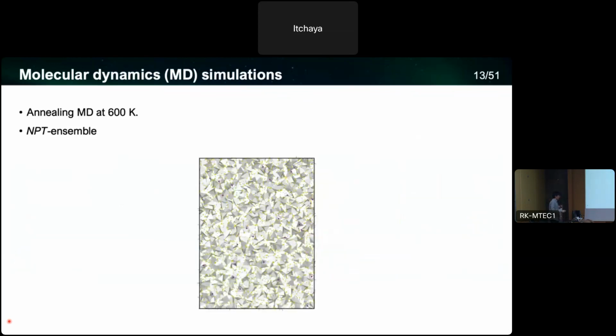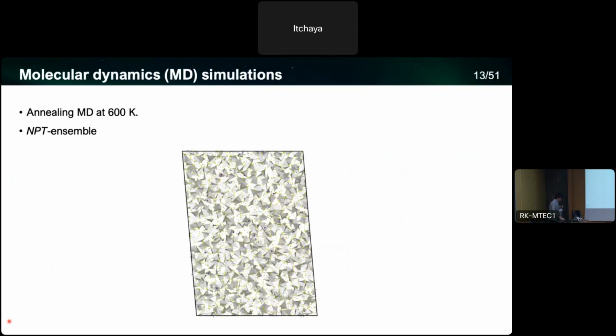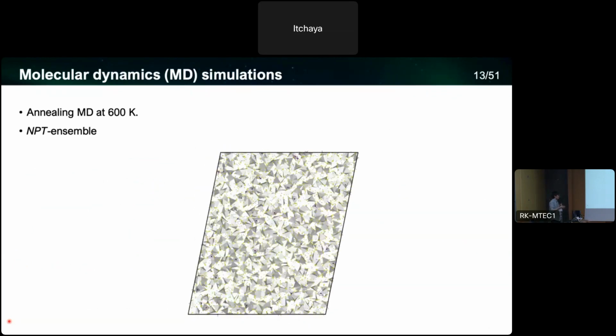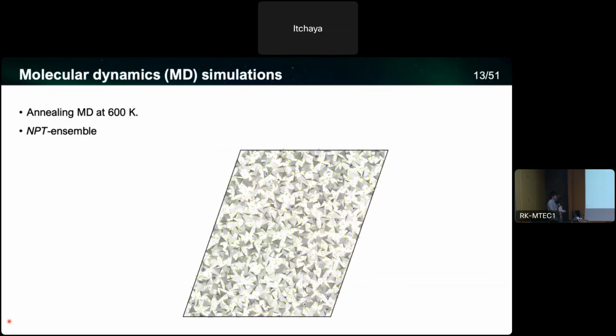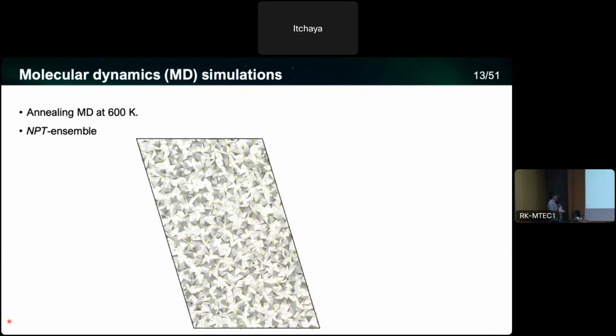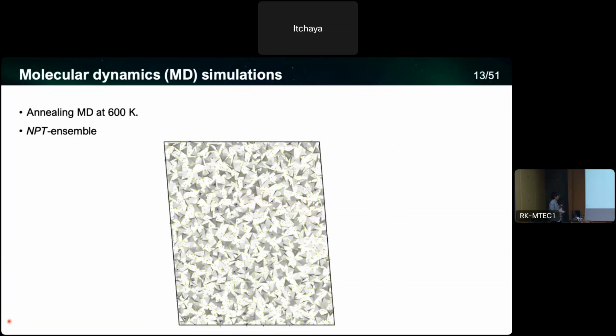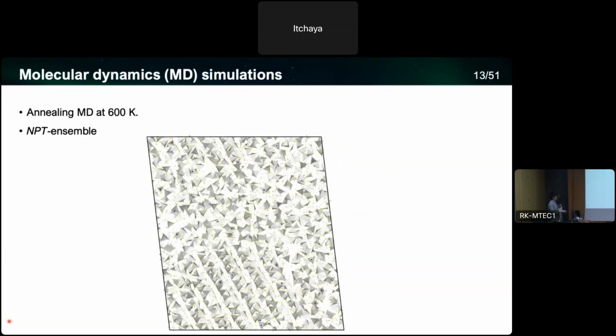Then from those glass structures, we need to do some heat treatment, again by molecular dynamics simulations. In this molecular dynamics simulation, we anneal at 600 Kelvin, and for the ensemble, we use NPT ensembles. Here is the animation of the molecular dynamics simulation. One frame corresponds to 1 nanosecond. And if you look at the part at the bottom, you will see the crystallization from here.